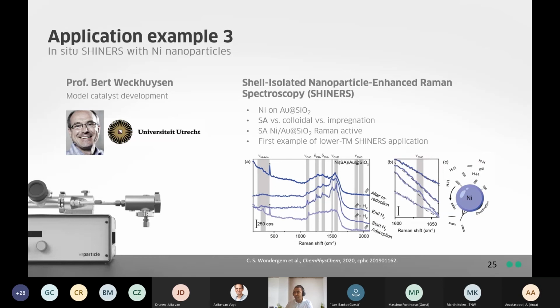And what they found in this study is that spark ablation was the only technique that yielded a Raman active catalyst at the end, and in doing so, it was able to be used for this Raman study. And this study was the first example in which a lower transition metal, so a first row transition metal, was used for a SHINERS application. And the study came out at the beginning of last year.